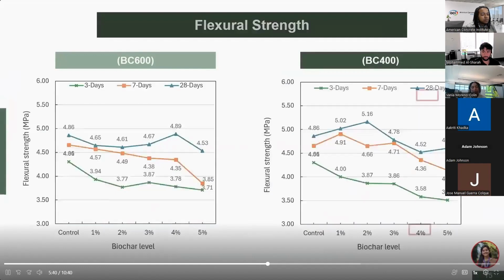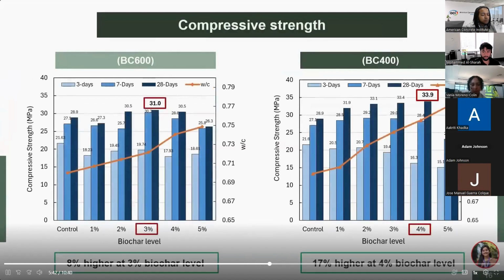From the compressive strength results, BC 600 showed an increase in strength up to 4% replacement with the optimum value of 31 MPa at 3%, which is about 8% higher than the control. In contrast, BC 400 exhibited strength improvement at every replacement level, reaching a peak of 33.9 MPa at 4%, which is 17% higher than the control. These findings highlight that incorporation of biochar at lower percentage can effectively enhance the compressive strength.